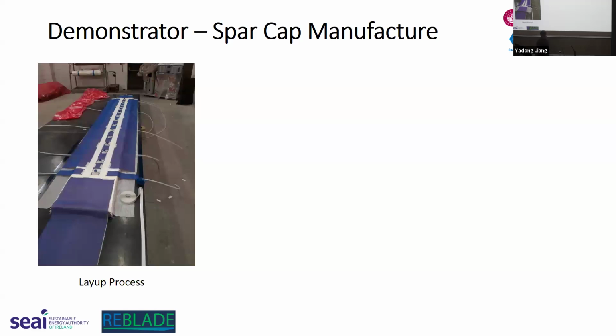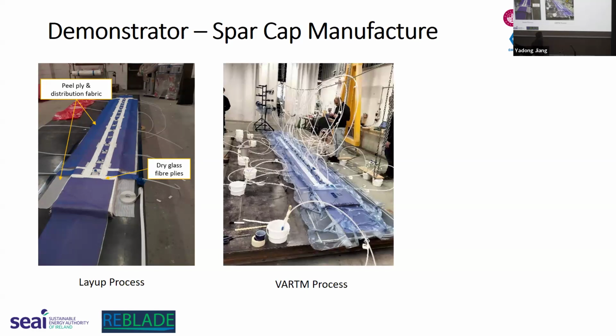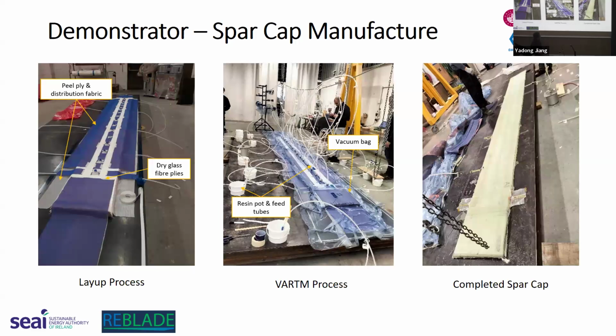Then moving on to the spar cap, we have the layup process, which includes the peel ply and distribution fabric again to allow the resin to flow efficiently. And then we have the dry glass fiber plies stacked up. So there's a good thick section of glass fibers, and it tapers off towards the tip. Then this is the VARTM or infusion process. We have the resin feed pots all along the sides, and the maze of tubes are all the resin feed tubes to get the resin into the part. And then you have the vacuum bag covering everything. This is what the completed spar cap looks like once we demold it and take off all the consumables and vacuum bagging.